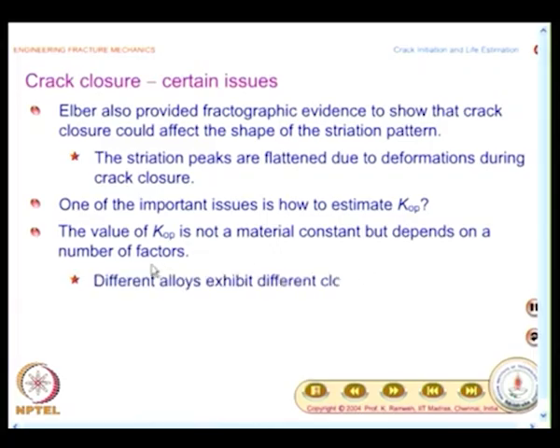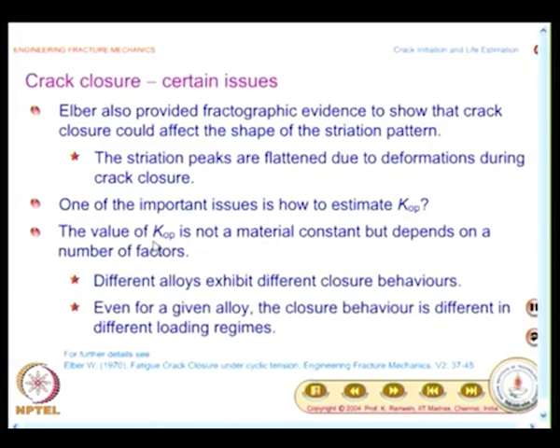And you have to note, unlike the fracture toughness, K opening is not a material constant, but depends on a number of factors. So, that makes the problem difficult. Different alloys exhibit different closure behaviors. So, this is one observation. So, you have to do a lot of tests to find out. Even for a given alloy, the closure behavior is different in different loading regimes. So, that makes the problem much more complex,